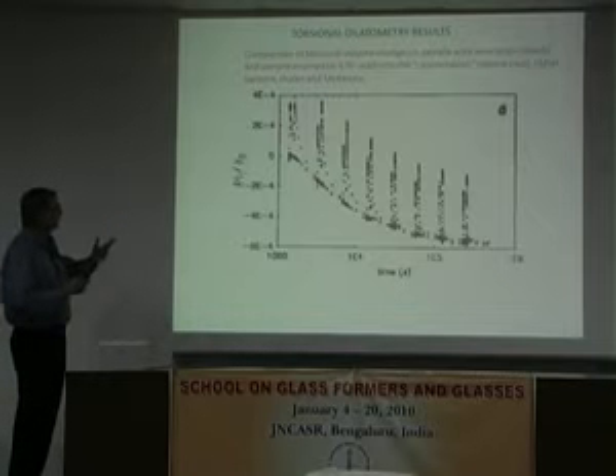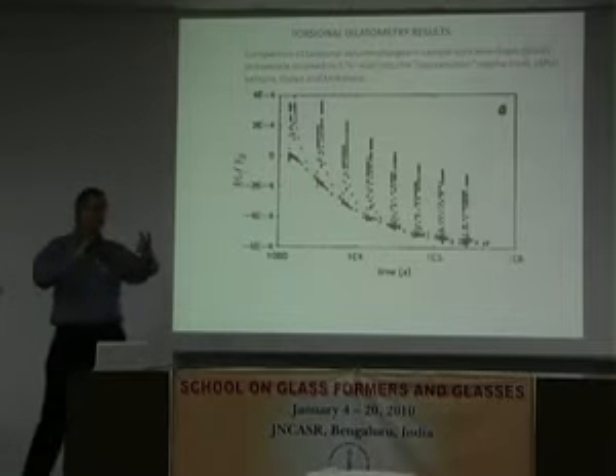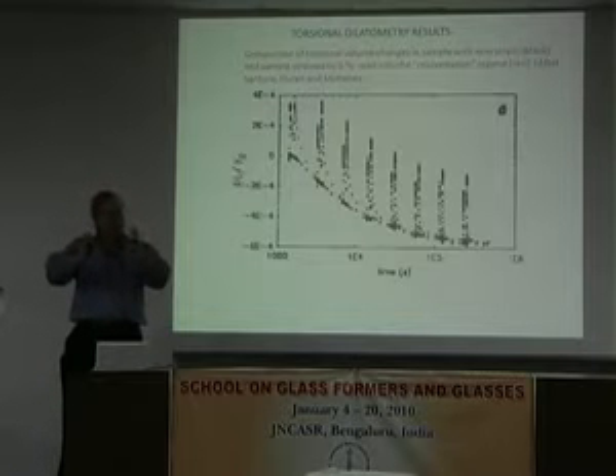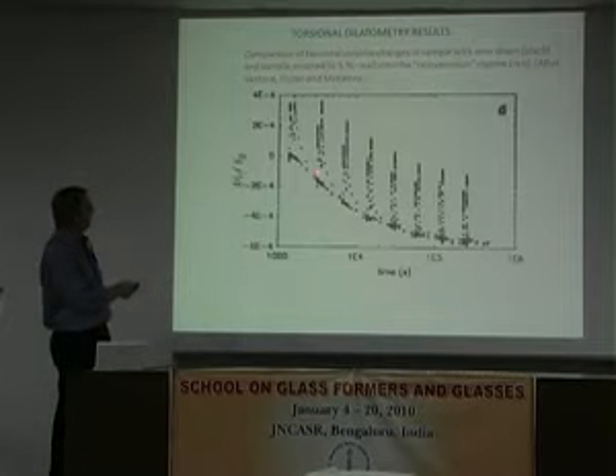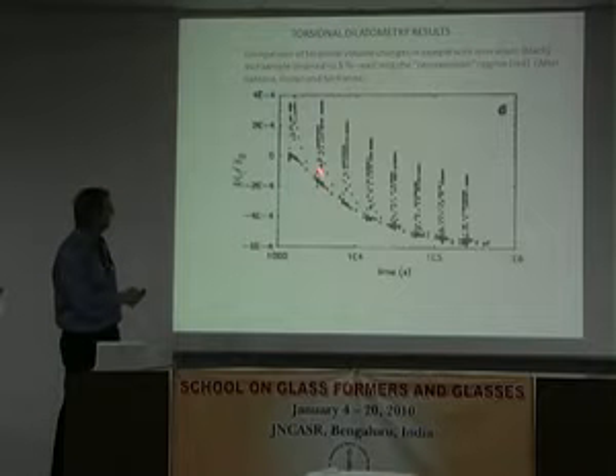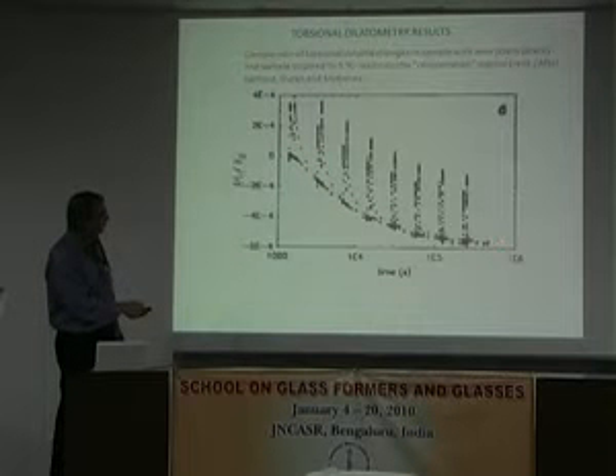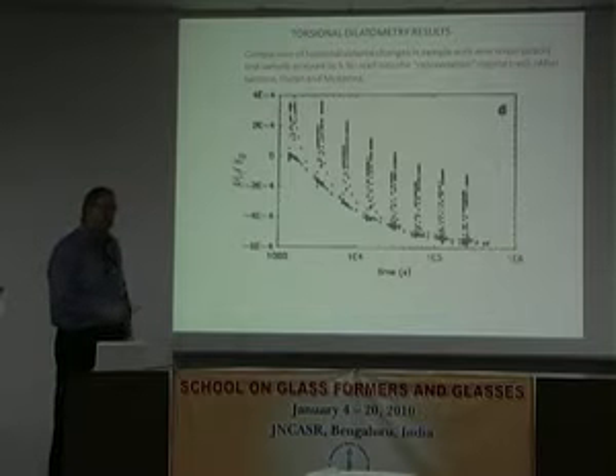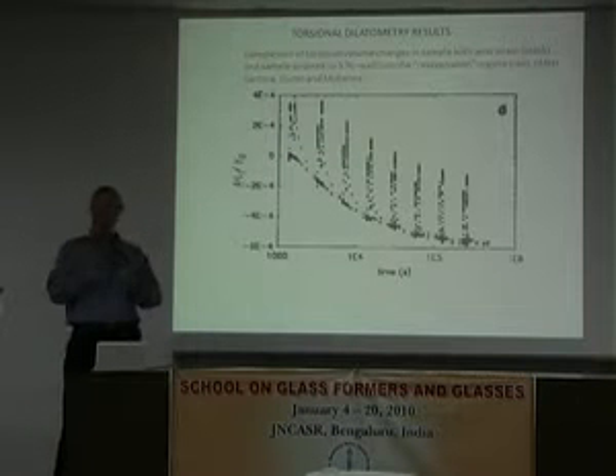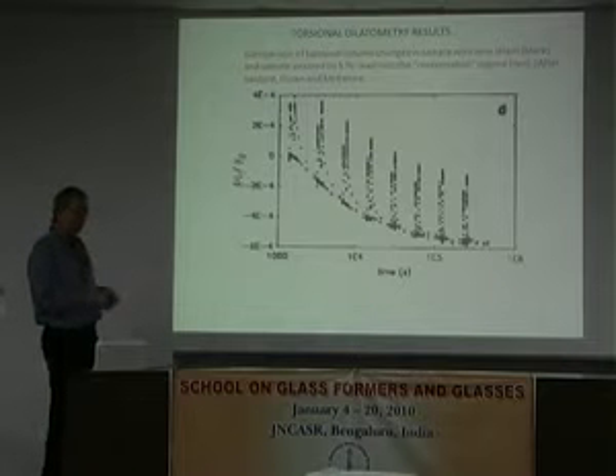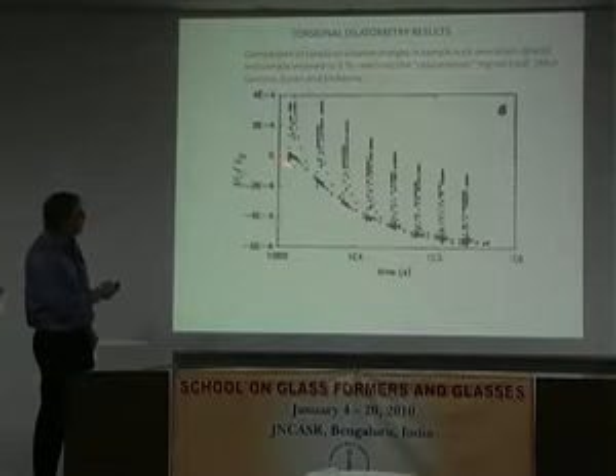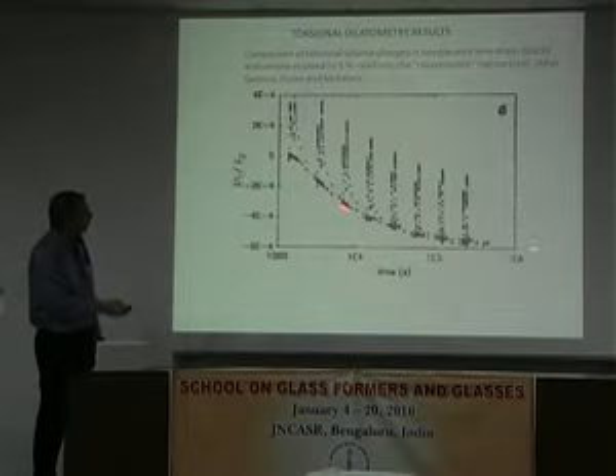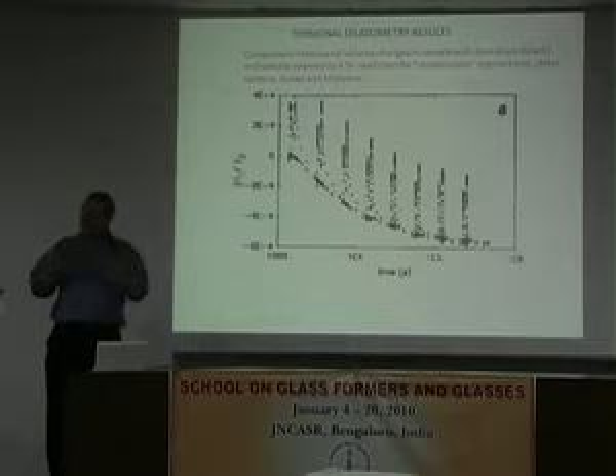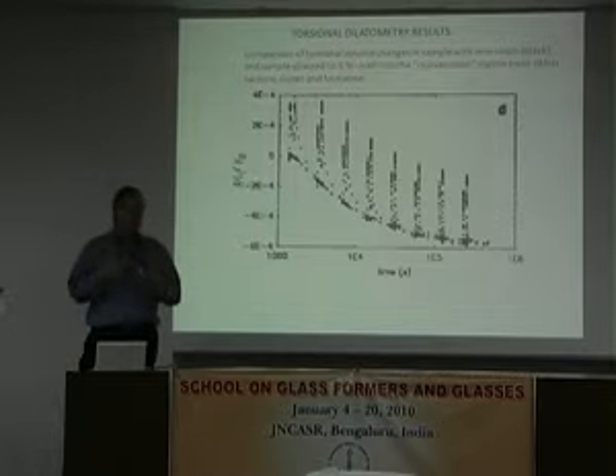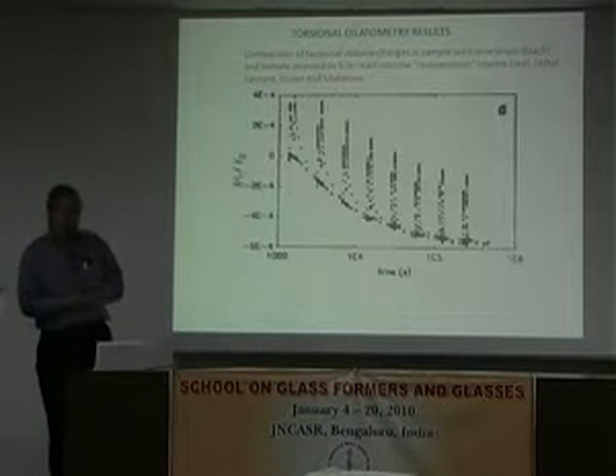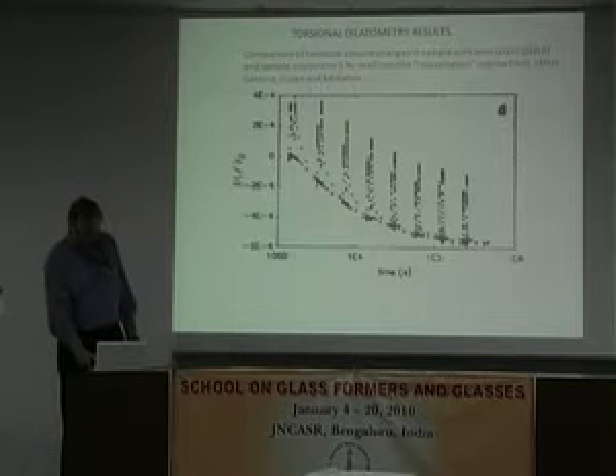Well, the next graph shows it. You can't see very much difference except you see these big spikes. So those big spikes are the volume change due to the mechanics. Okay, they're second order, so they're actually quite big. We were quite surprised. We didn't expect to see that big a change, but we did. And then here's the underlying volume recovery where you can't distinguish the two. So in fact, at least for this particular set of experiments we ran close to the glass transition and so forth, we see that there's no evidence of a delayed volume recovery due to the applied mechanical deformation. So this argued against a simple rejuvenation hypothesis or simple erasure hypothesis.